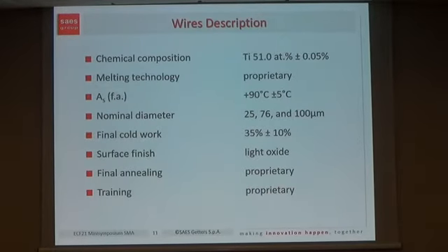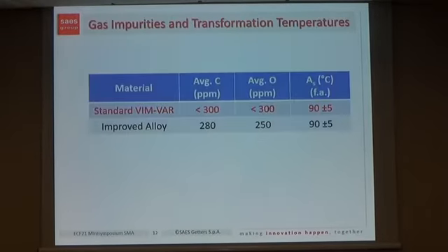The results are a comparison between our standard 25, 76, 100 shape memory wires. Smart flex wire is our standard trained actuators, titanium rich, standard AS 90 degrees C, and we prepared ingots with a new combination of melting and processing, keeping everything else constant at the end in terms of cold work, surface finish, final annealing and training, in order to neutralize as much as possible the secondary effects on fatigue behavior. We also check the gas impurities and transformation temperature.